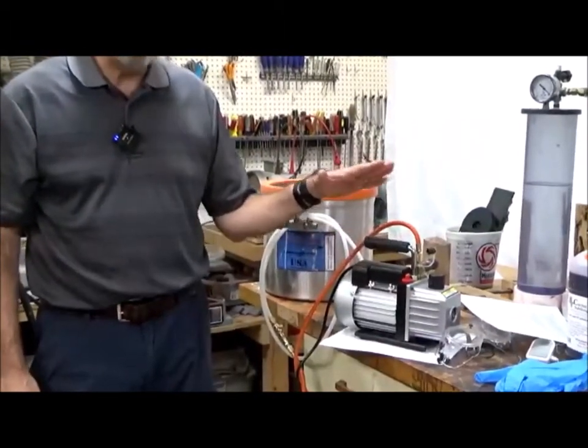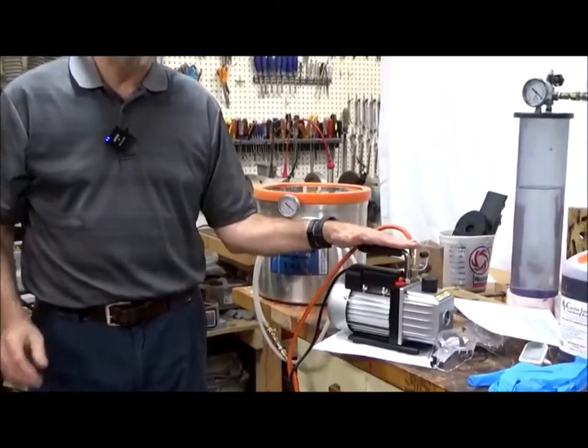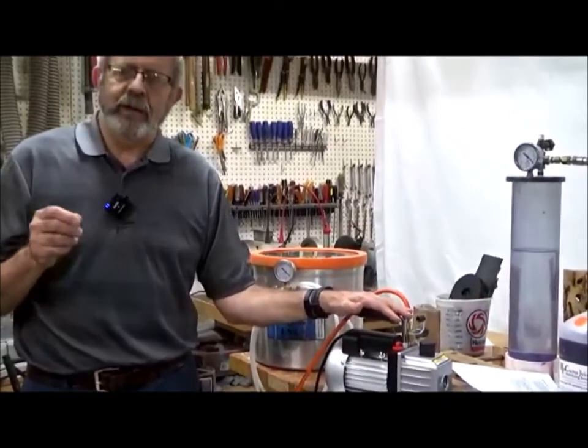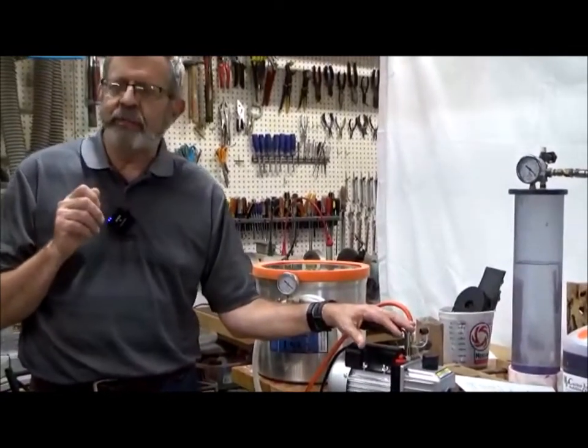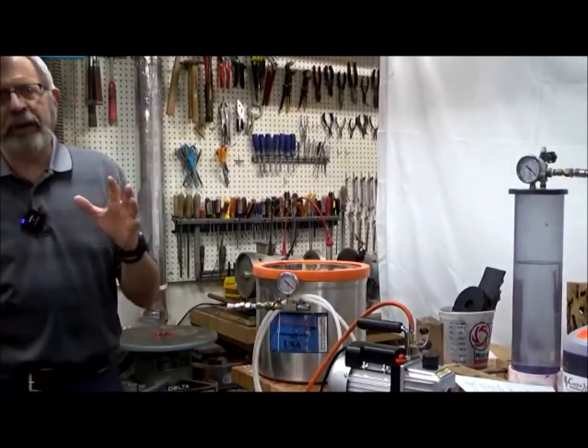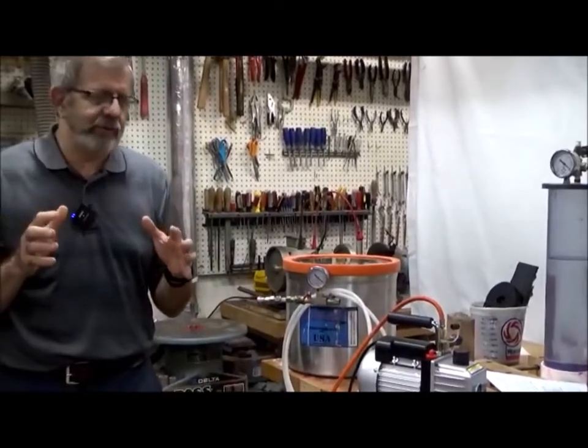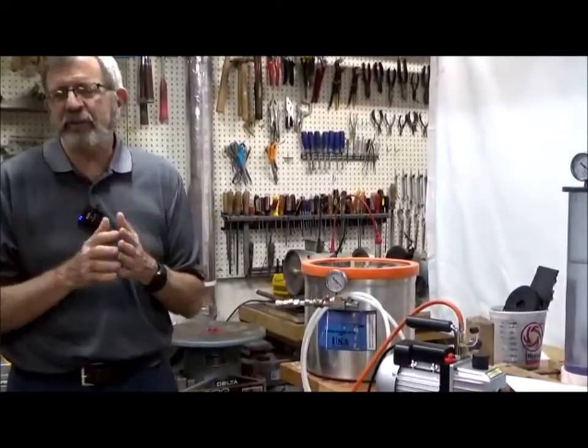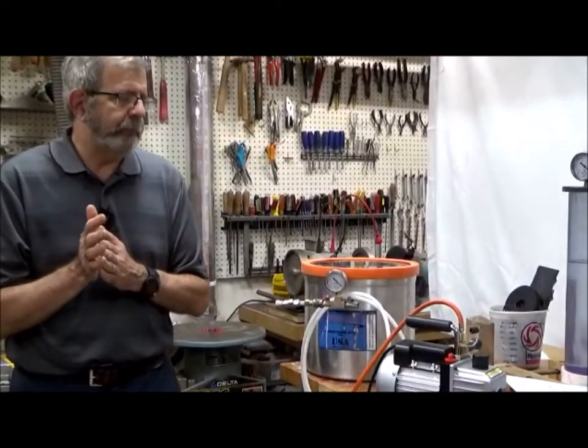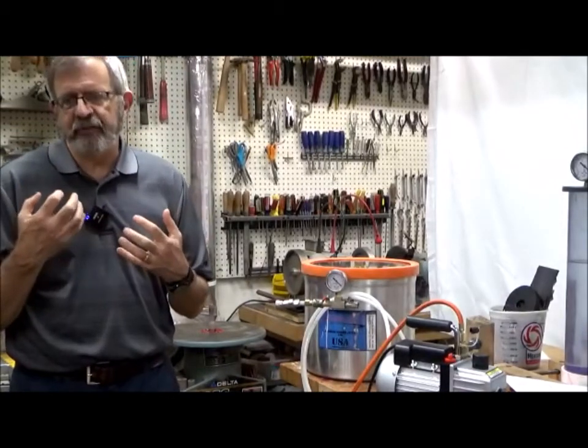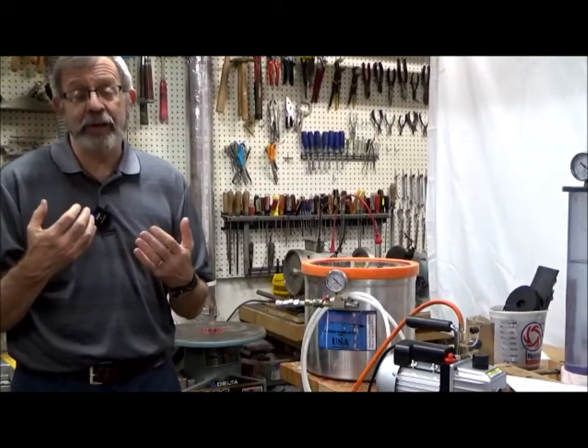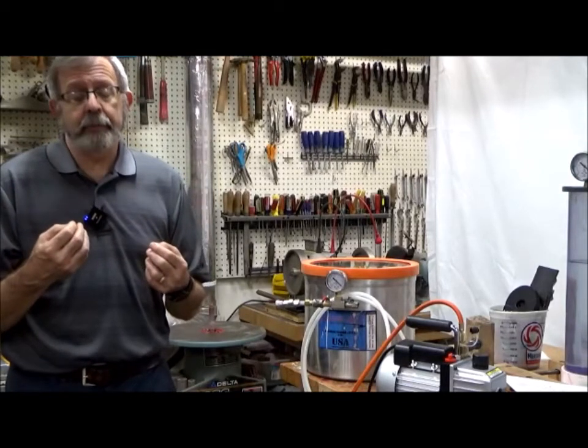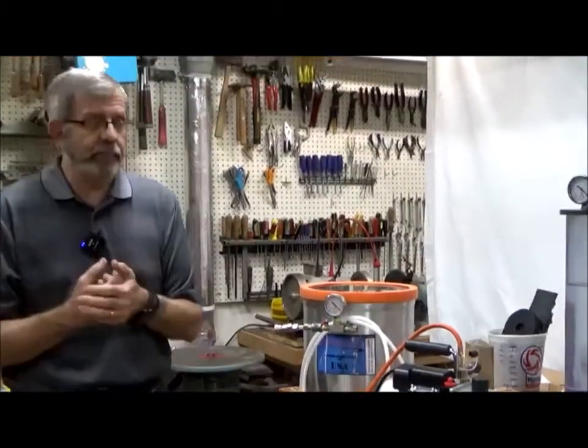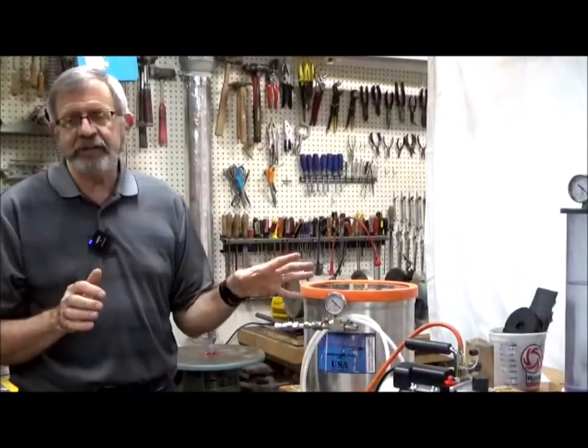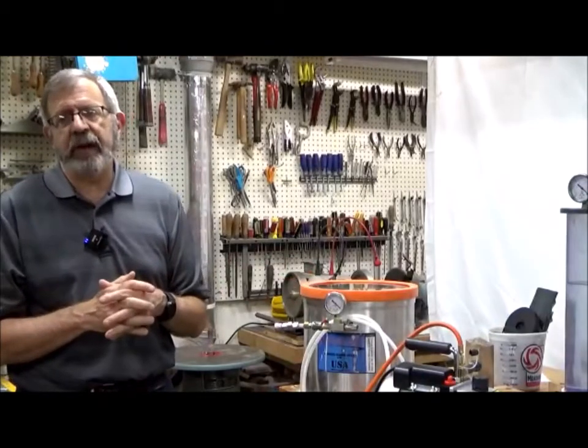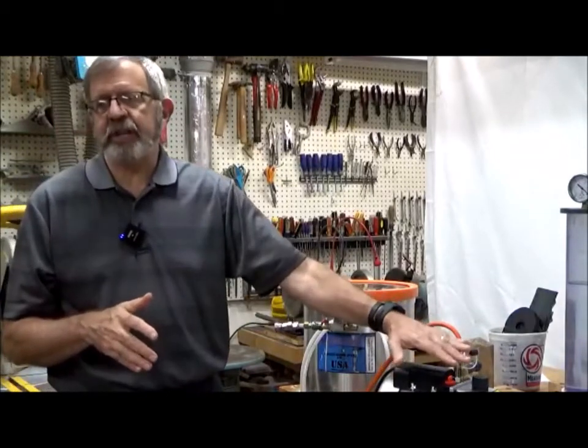And what's important with the vacuum pump for this application is you don't need to move a lot of air. But what's more important is you need to be able to get to 27 and whatever the theoretical maximum is for your altitude for your maximum vacuum. Around here, it's about 27 and a half inches of mercury. But you want to be able to pull that full vacuum. It doesn't have to pull a lot of volume like your vacuum chuck may need to do on a piece of porous wood, but it does need to pull a high vacuum, and the HVAC pumps are set up to do that.